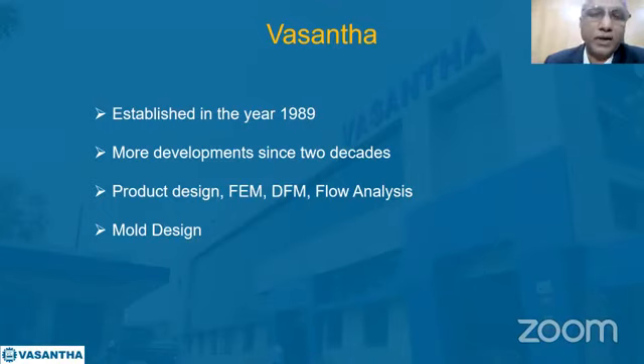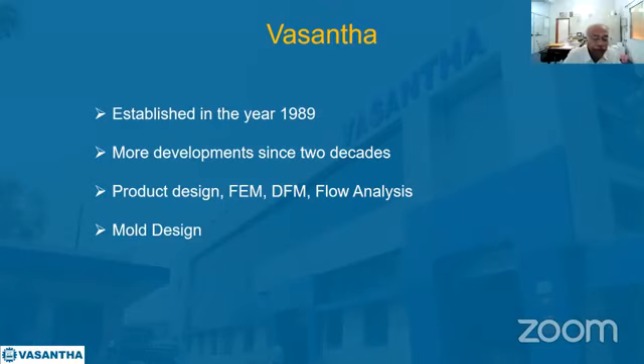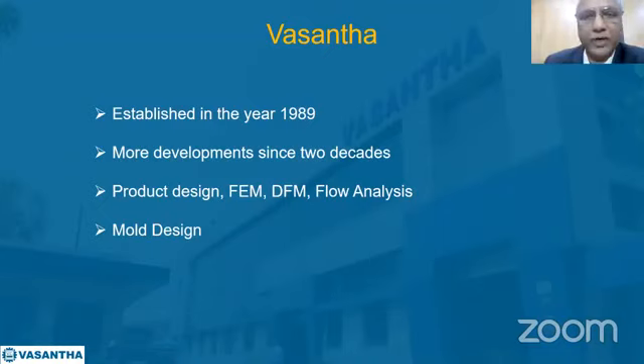Copper itself is a high conductor of heat, but by alloying it with beryllium, it attains a hardness of 40 HRC. The commercial grades available in the market today are at 40 HRC, and are used to reduce the cycle time due to their high thermal conductivity, also without compromising on hardness, because 40 HRC is good enough for some molds, say medium life or low life molds. So the life of the mold is not compromised.